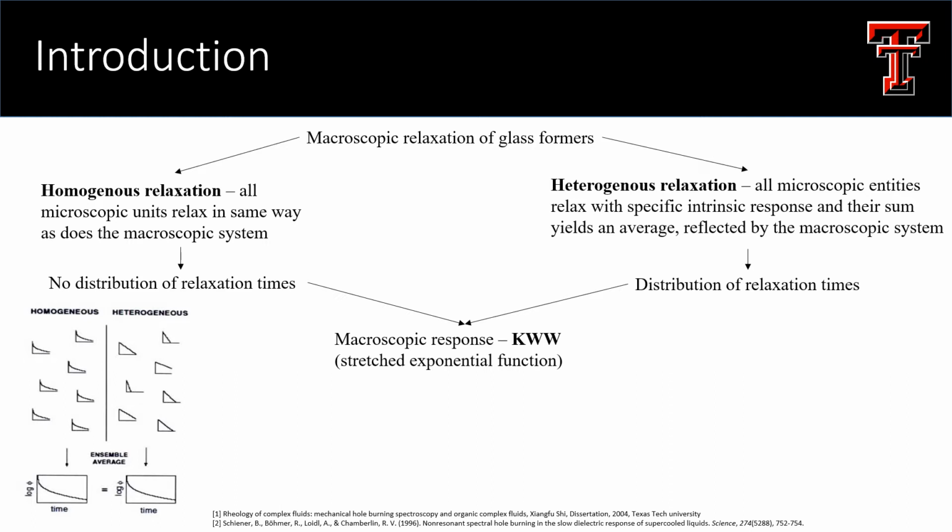The idea of microscopic heterogeneity in macroscopic glass forming systems can be traced at least to the ideas of Adam and Gibbs in 1965. They attributed the dynamic slowing down that occurs when materials approach their glass transition to the increasing length scale of cooperatively rearranging regions.